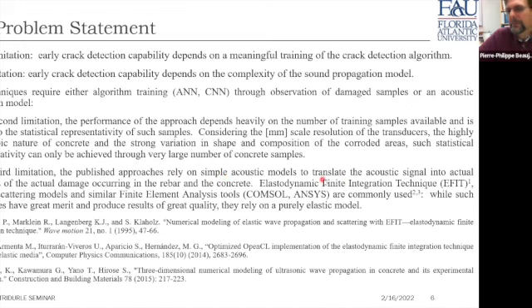Now, in the third limitation, which is listed over here, the published approaches rely on simple acoustic models to translate the acoustic signal into actual estimates of the damage occurring in the rebar and in the concrete. Now, there are modeling techniques such as the elastodynamic finite integration technique, or EFIT, volume scattering models, and finite element analysis tools such as COMSOL and ANSYS, which are commonly and extensively used.